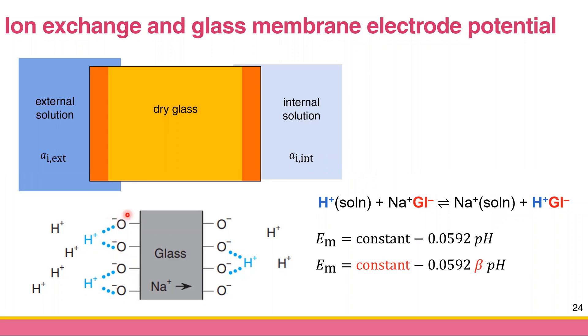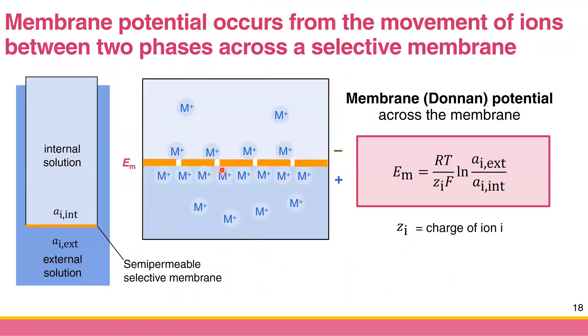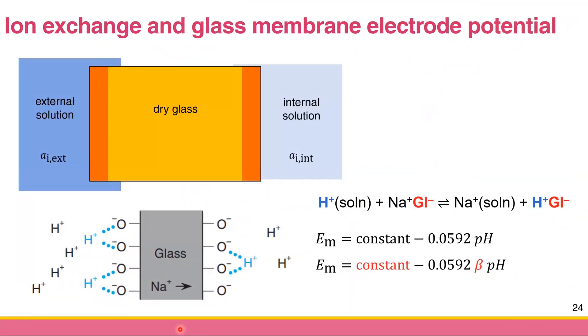To visualize the process: your glass has silicon oxide, represented as a negative site, which binds cations. If your external solution has more protons, you get more positive charge on that side; if your internal solution has fewer protons, you get less positive charge. Just like a membrane with different ion concentrations on each side, the glass membrane selectively binds protons — more on one side, fewer on the other — generating a membrane potential.